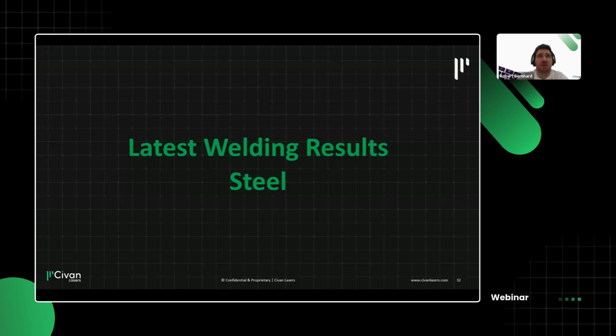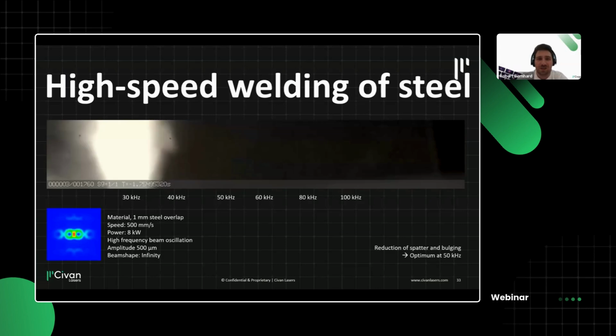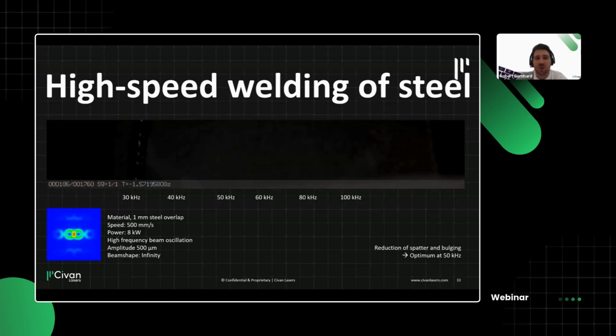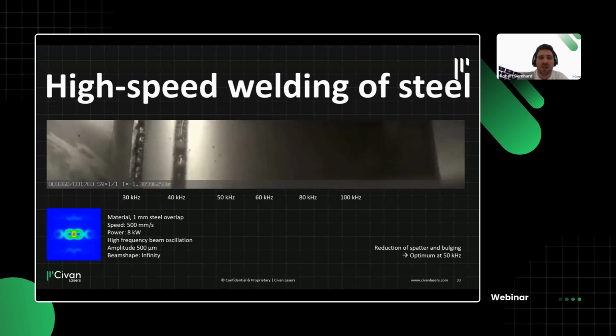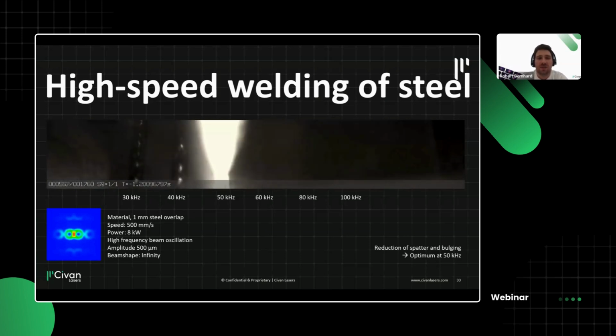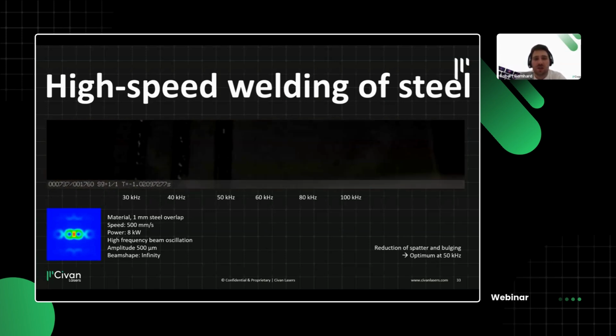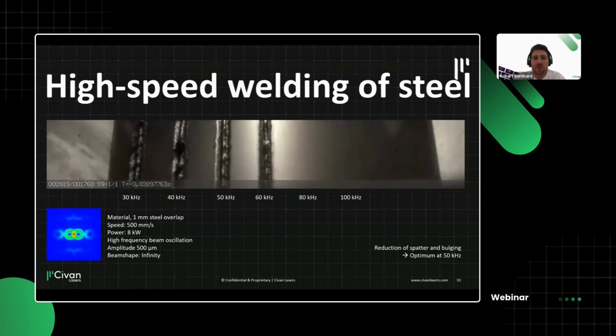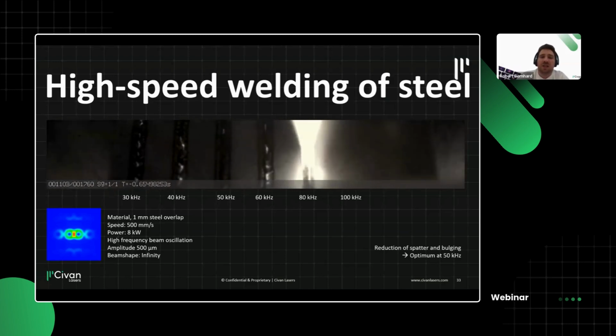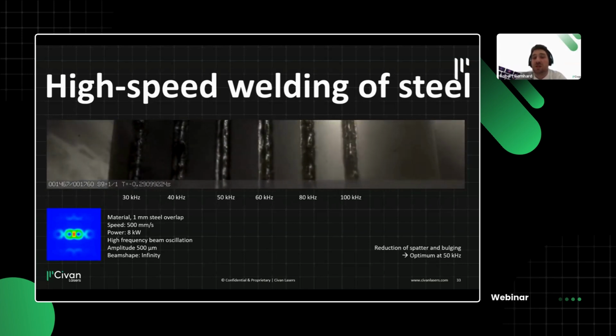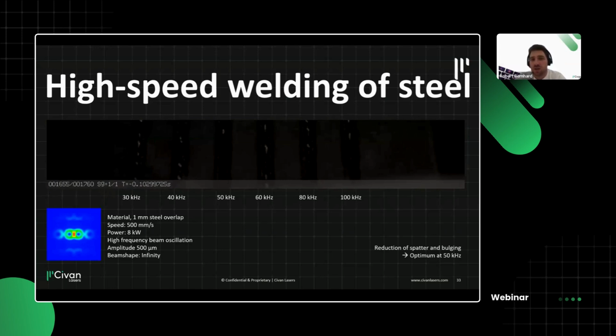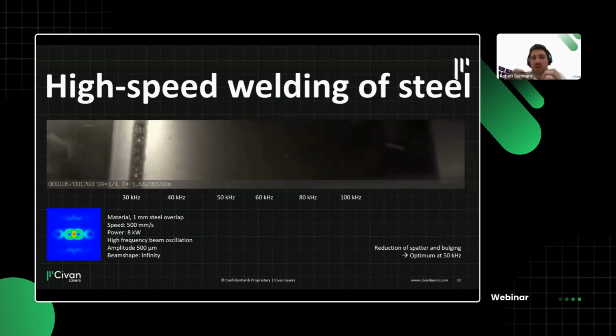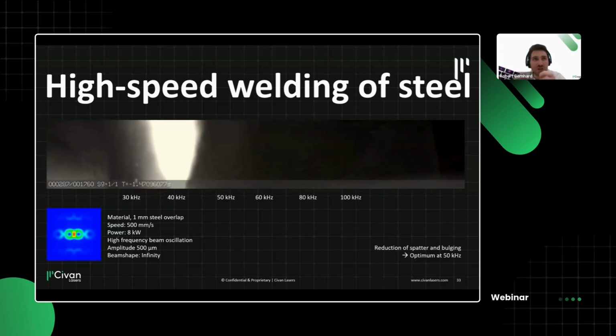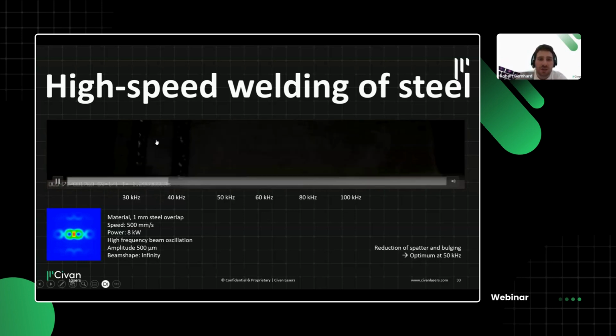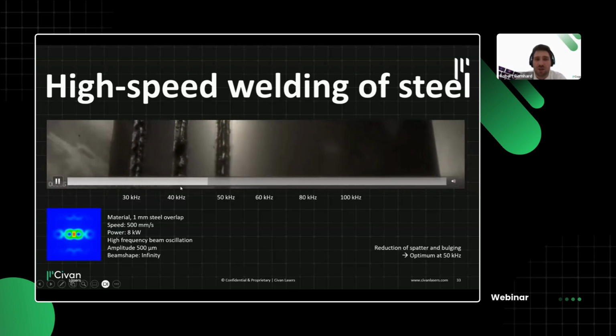Finally, and I hope you're still interested, on this topic of high-speed welding, is welding steel. And this is steel welding at 500 millimeters per second, which is pretty fast, for a 1 millimeter overlap. The challenge you usually get with this high-speed welding is that you get bulging, where the molten material bulges or adheres together, and you get these bubbles or these problematic zones here.